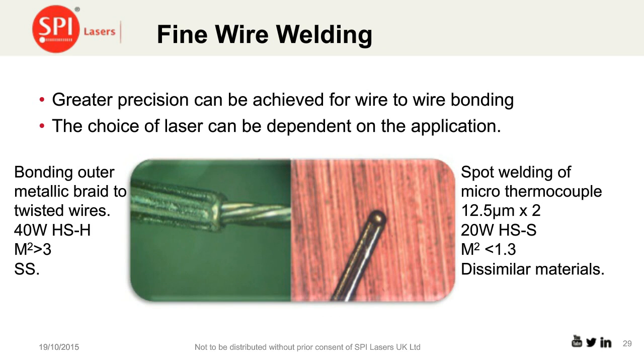We can move on, and there's a whole plethora of different applications where this greater precision can be achieved for wire-to-wire bonding. And basically, the choice of laser is dependent on the application. So here are two examples that I'd like to bring to your attention, where in one, we're trying to weld or join a metallic braid to a wire going through it. And here we need to do some gap bridging. So the ability to have a laser beam with a slightly higher M squared, or less beam quality to some people, a broader energy distribution, also comes with higher pulse energy. That's one of the trade-offs that being able to play around with modes with fiber lasers gives you. We can bridge that gap. It produces a larger spot, but that's what's required when you're trying to bridge gaps.